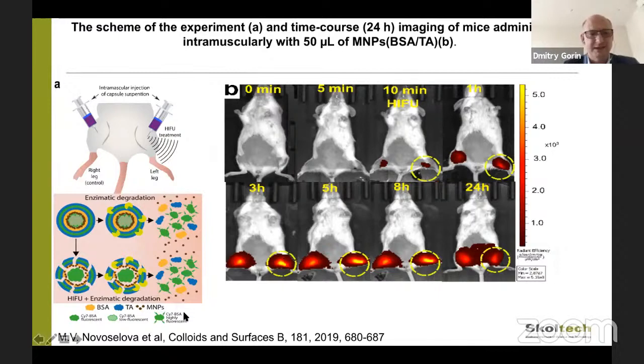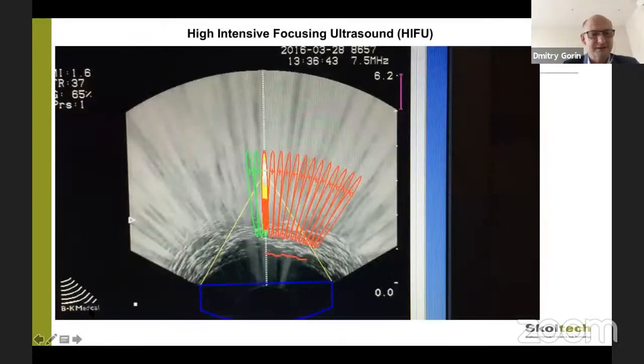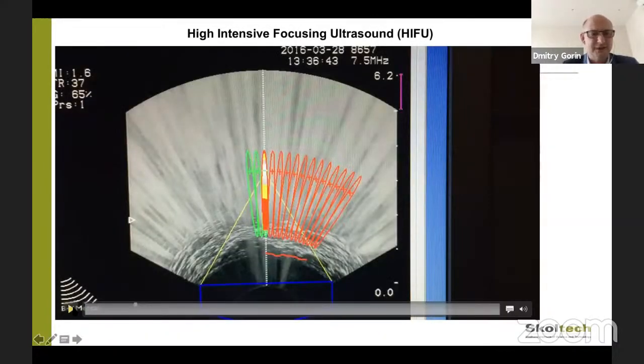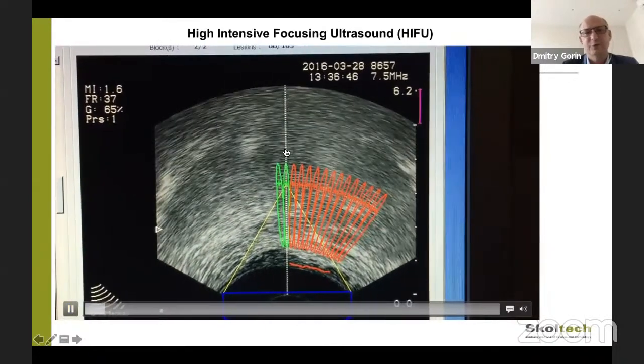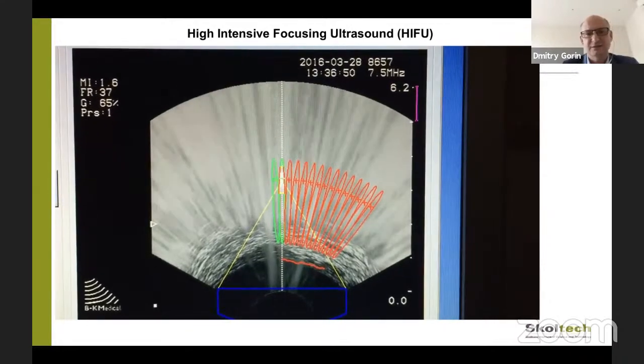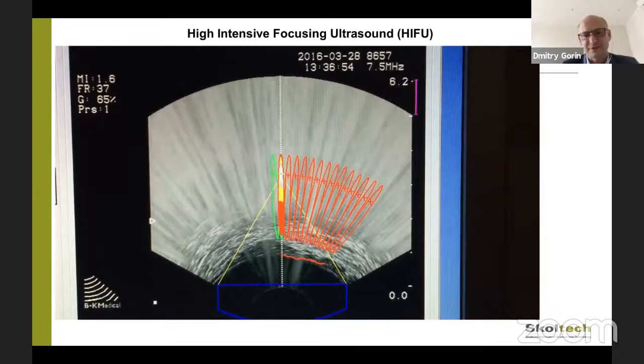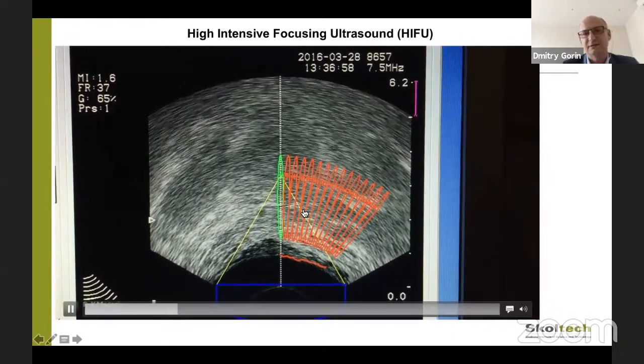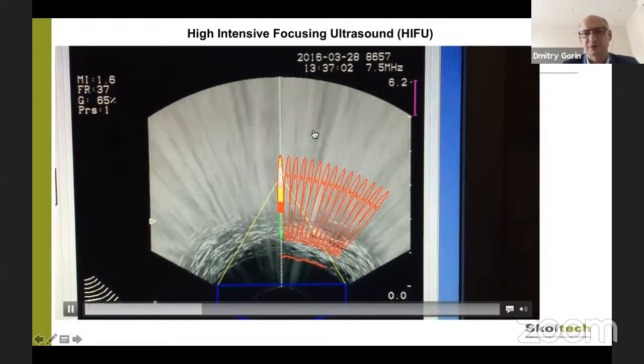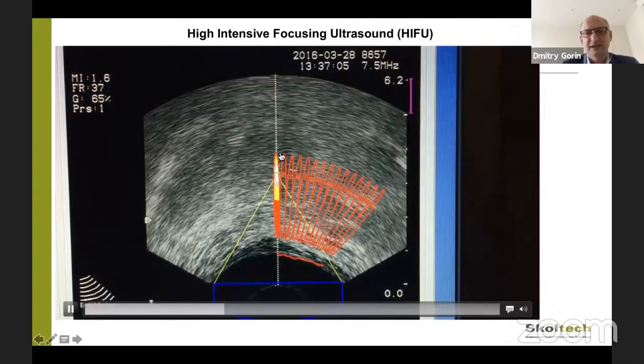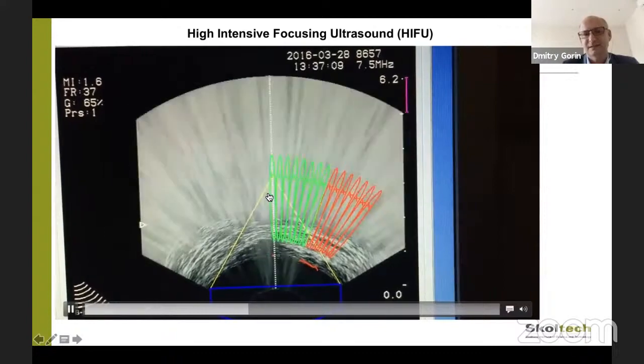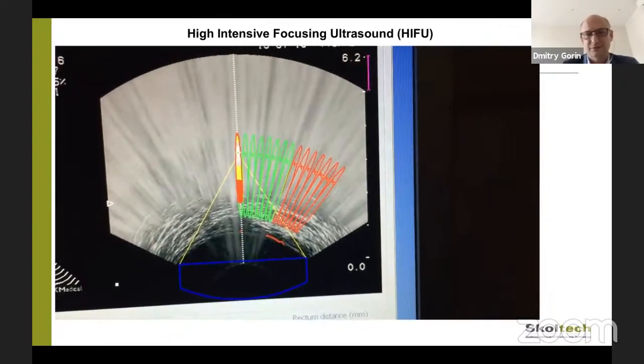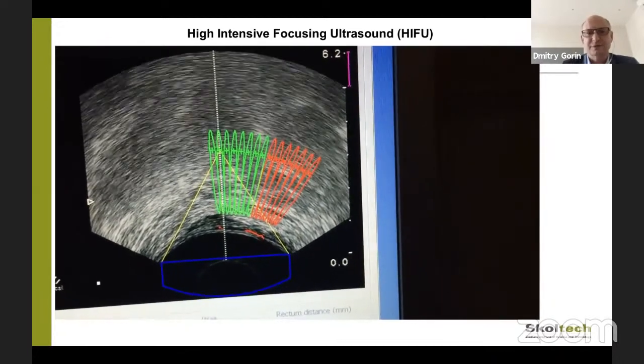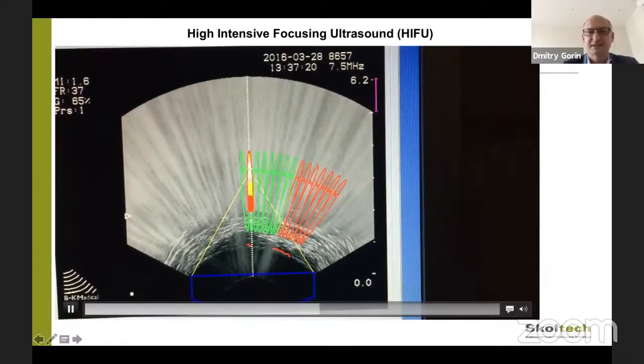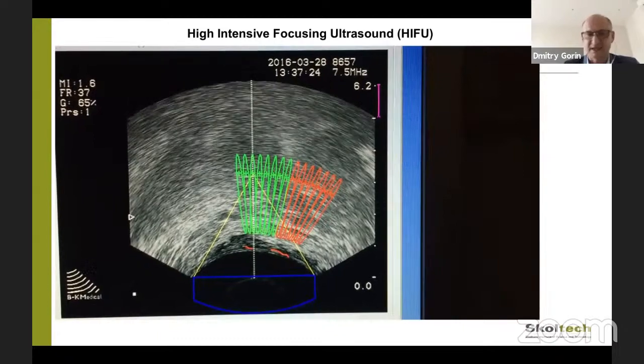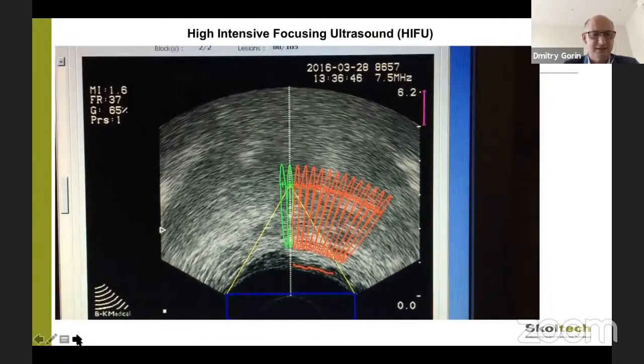Why? Because now this method is used in the clinic. It's high intensity focused ultrasound. Here you can see a movie from a real operation. This method is used for hyperthermia of prostate cancer, under control of ultrasound imaging. We can switch on high intensity focused ultrasound and then induce hyperthermia and, as a result, necrosis of cancer tissue. And it is very important that we can use the same ultrasound but at lower power density for opening our microcapsules in vivo. And then I would like to go to the conclusions.